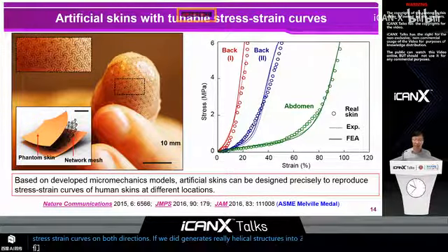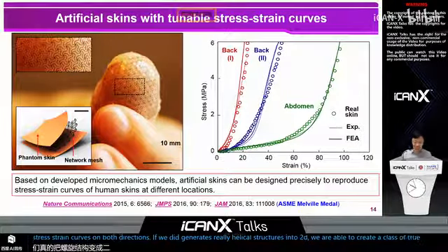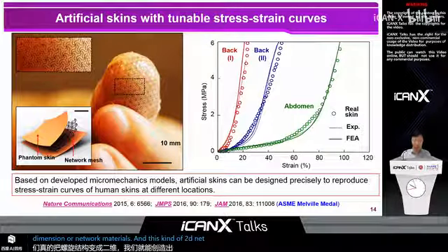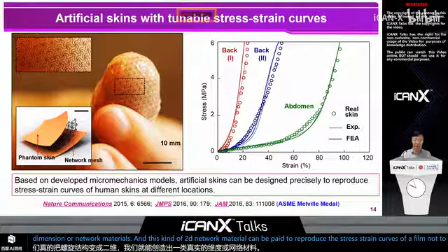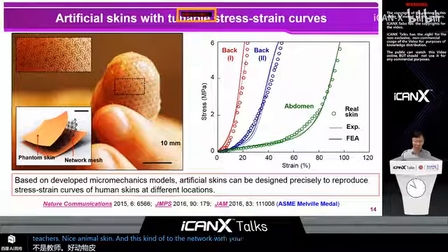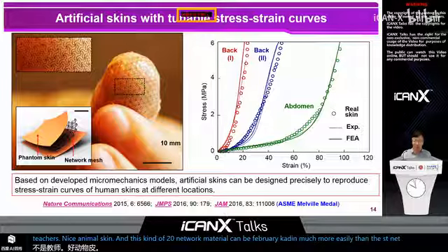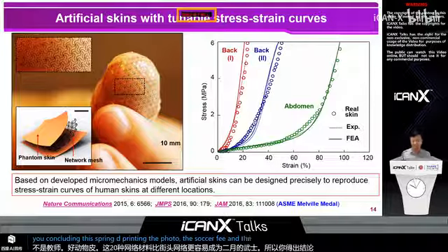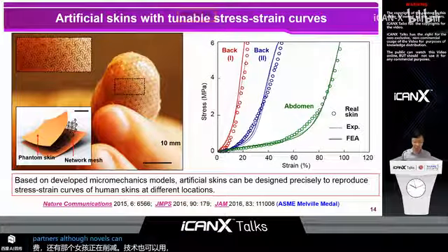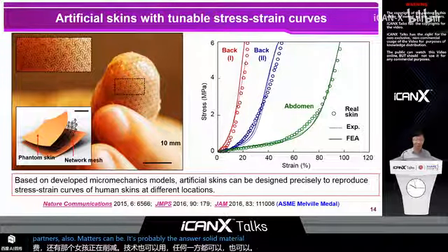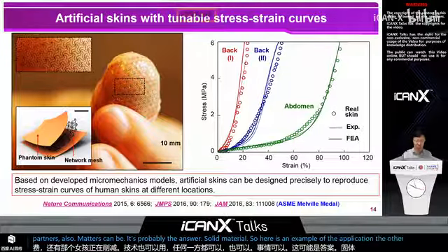If we degenerate the 3D helical structures into 2D, we are able to create a class of 2-dimensional network materials. And this kind of 2D network material can be tailored to reproduce the stress strain curves of film-like tissues, like animal skin. And this kind of 2D network material can be fabricated much more easily than the 3D networks. So excluding the 3D printing, the photolithography and the laser cutting technologies can also be used, and either the polymers or the metals can be exploited as a solid material. So here is an example of the fabricated network wrapped onto the tip of the thumb.